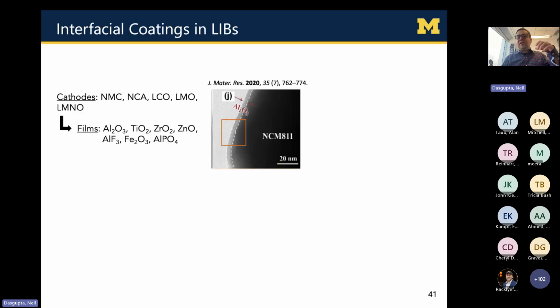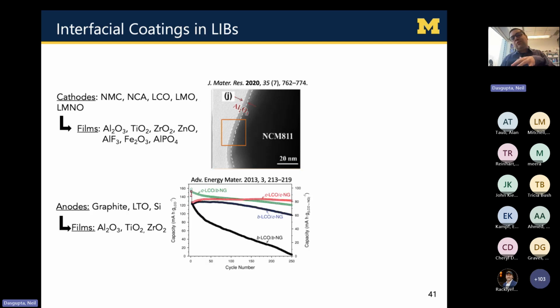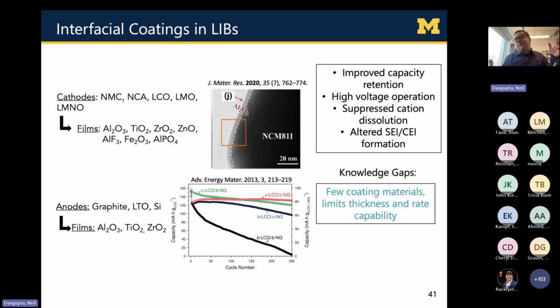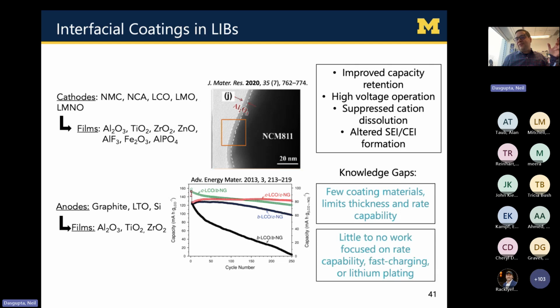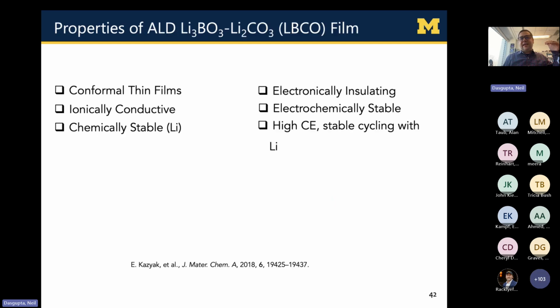And so we really looked to the literature of all the different coatings. Obviously, a lot of work has been done on coatings in lithium-ion batteries. Most of the coatings are on the cathode side of the battery. And one of the key enabling technologies, which we use as well, is atomic layer deposition, or ALD. You can see companies that are commercializing ALD coatings for enabling high voltage cathodes. Interestingly, there's actually a lot less work on this idea of artificial SEI coatings on the negative electrode or anode side. And most of what had been tested in the literature are these simple binary metal oxides like alumina, titania, that actually are pretty lousy lithium ion conductors. So the knowledge gap is here really, there's little to no work before this that focused on fast charging and rate capability by looking at coatings on the anode side.